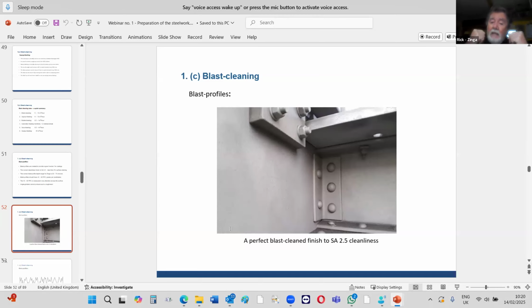And the blast profile is the main anchor. So it's going right inside that profile and giving you your grip. And that's why, if you have a blow from the side, like on crash barriers and bridge supports, if it's hit, it can shear off some of the zinc. If you've got 15 tons of lorry, you won't stop that from damaging the zinc layer, but it'll rub it across the top, but inside you still have Zinga. So if you go the next day or so, the next week, and put it on with a brush, it'll adhere to the existing zinc and it'll rebuild again. So that's a very key factor.